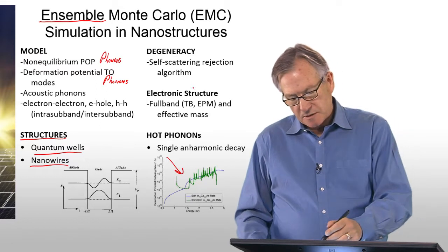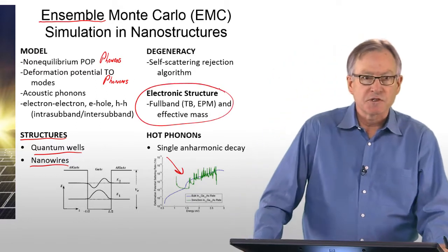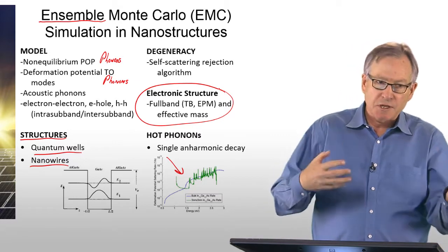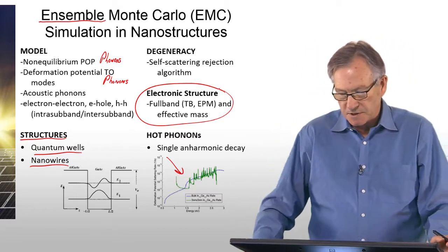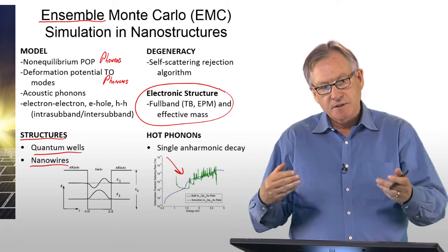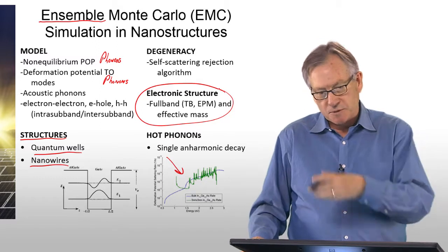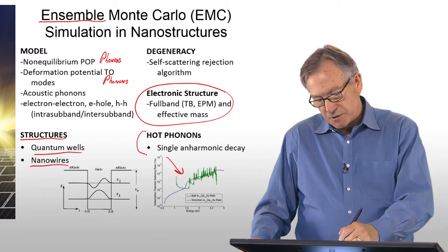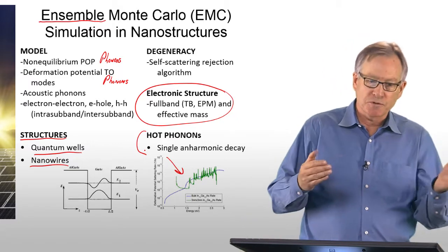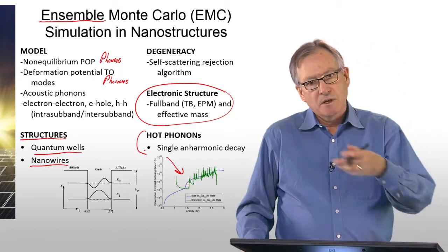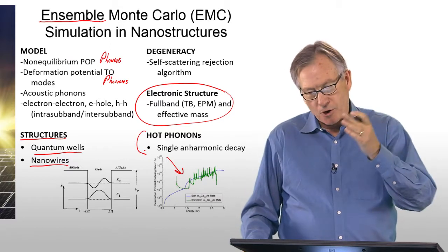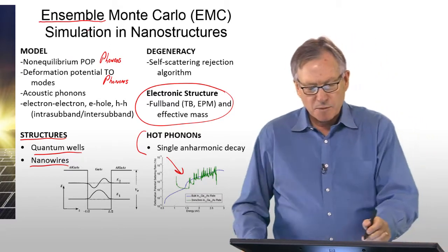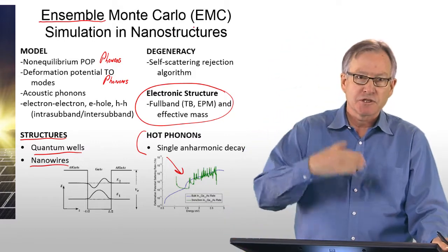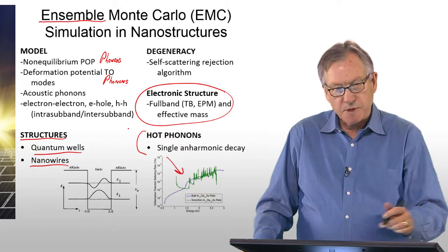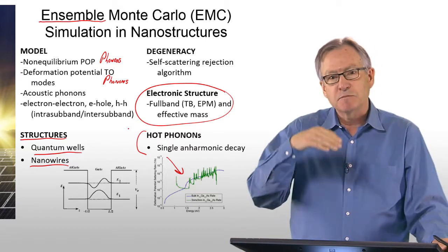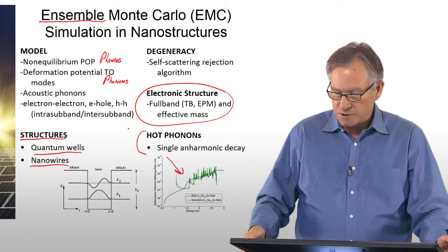So there's other things that can be affected, but in particular, we try to include the full band structure into these calculations, and that is that we use an electronic structure calculation in order to get the electronic structure, and then we use that as the states between which electrons scatter in a full band picture of transport in the material. We also consider basically the motion of phonons, and so you can treat phonons also within the framework of Monte Carlo. You can treat the particles, the phonons themselves, within an ensemble Monte Carlo approach, and you can keep track of their population, and you can account for the fact that the phonons may move out of equilibrium just like the electrons can, and that becomes important in some concepts like hot carrier solar cells, which I'll talk about.